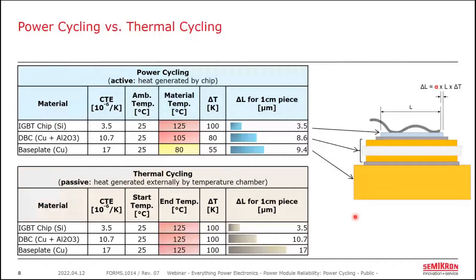So if we turn on this module at full power in a 25 degrees Celsius ambient, and it's dissipating some known amount of power in the form of conduction losses across the silicon, we might get a 100 Kelvin rise in the junction temperature above the ambient. This 100 Kelvin delta multiplied with the CTE of silicon for an example 1 centimeter length results in an increase of 3.5 microns and some associated stress where the chip is soldered down to the DBC substrate.